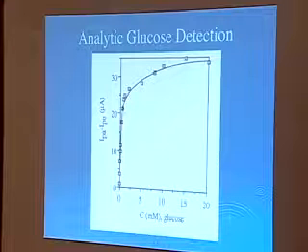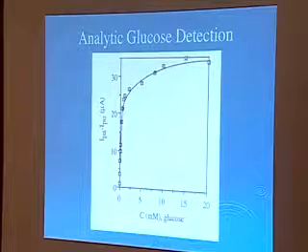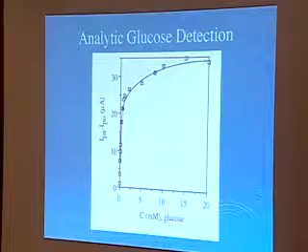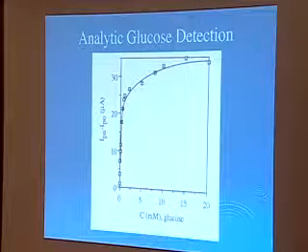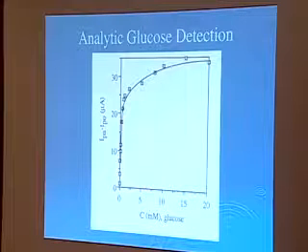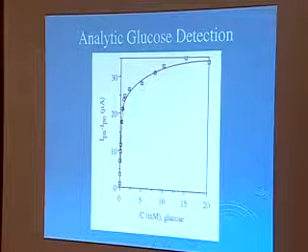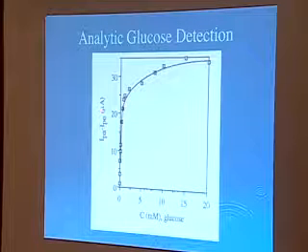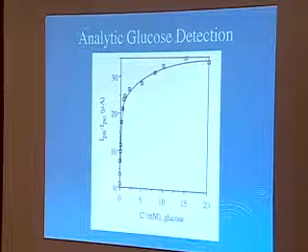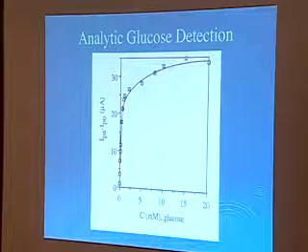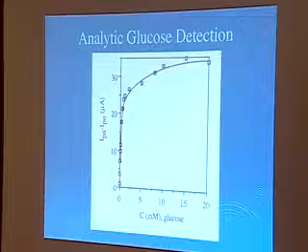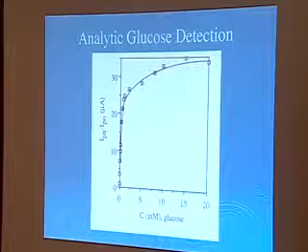We stop along the way when we have this puzzle and say, well, we don't know how it works, but it sure makes a great sensor. So we have the cobalt hexamine in there because we decided that was the best cation to use for the highest sensitivity. We're just doing cyclic voltammograms. We have the glucose oxidase, 10 micromolar in the solution, and we plot the difference between the modified electrode peak current in the absence of the glucose and in the presence of the glucose. And you see we get a plot like this as we increase the glucose. And we're actually going over a regime here from 0 millimolar to 20 millimolar. That goes way over the physiological regime, unless you're seriously ill. And you can see that we have two regions.